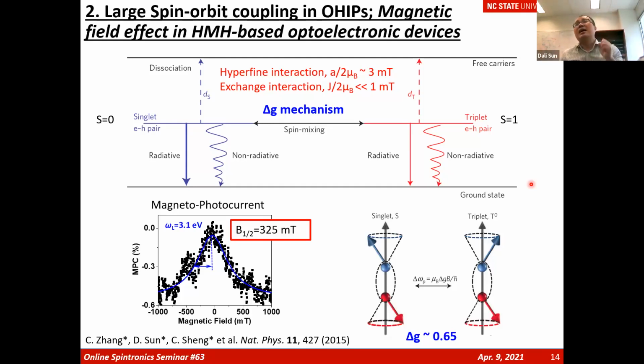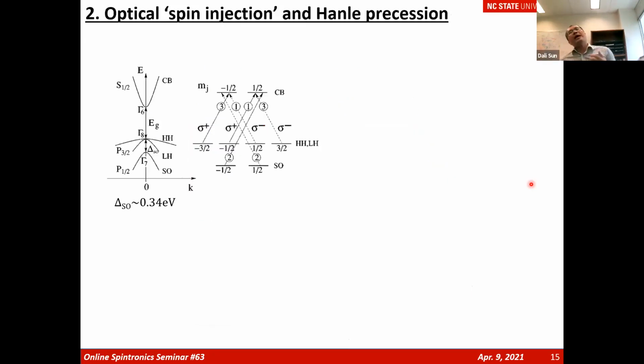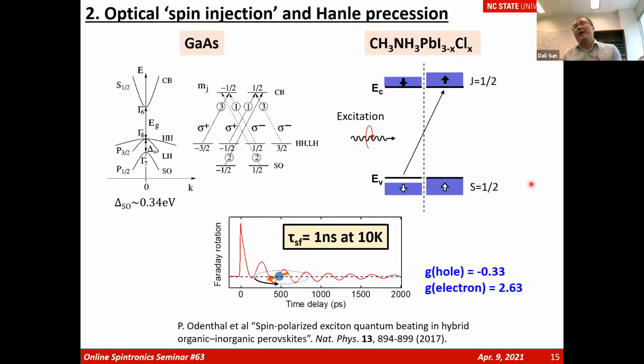That delta g indicates the electron and the hole have different g values, indicating a strong spin-orbit coupling interaction for these electrons. Then further on, we realized this hybrid perovskite structure is very similar to gallium arsenide. The gallium arsenide, due to spin-orbit coupling, forms the splitting bands, forming the S state and the J state. Hybrid perovskite does exactly the same thing, but with the reverse electronic structure, we form a J state in the conduction band, the S state in the bottom valence band.